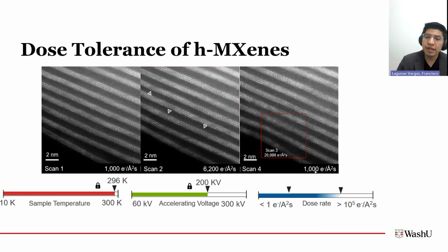So in red here, we have a scan that we did at 20,000 electrons per angstrom squared, way more than you would ever use during imaging, but really just to show a proof that the electron beam will come in and alter the local structure of your material. And we can even see some loss of crystallinity, which is more likely than not because we're knocking out atoms and reducing the local crystallinity of the material.